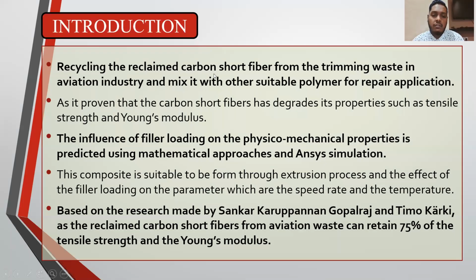For the introduction, the reclaimed carbon short fiber from the trimming waste in the aviation industry is recycled and mixed with another suitable polymer for repair application, as it is proven that the carbon short fiber has degraded properties such as tensile strength and Young modulus. The influence of filler loading on the physico-mechanical properties is predicted using a mathematical approach and ansys simulation. This composite is suitable to be formed through the extrusion process, and the effect of filler loading on the parameters, which are the speed rate and the temperature.